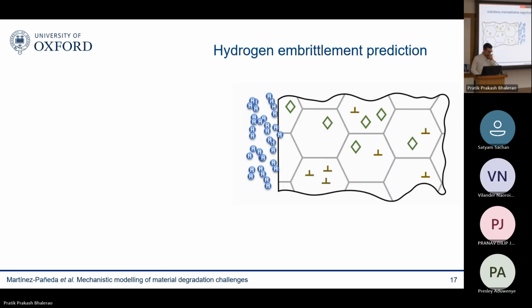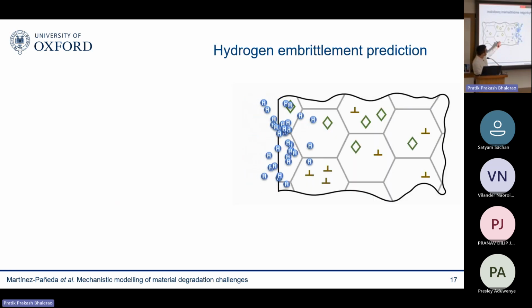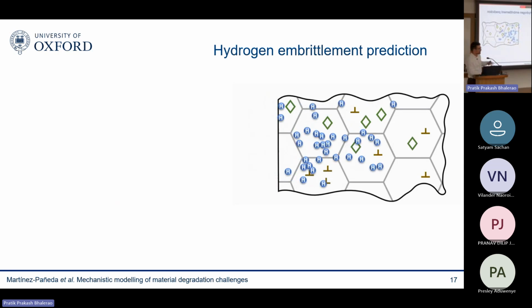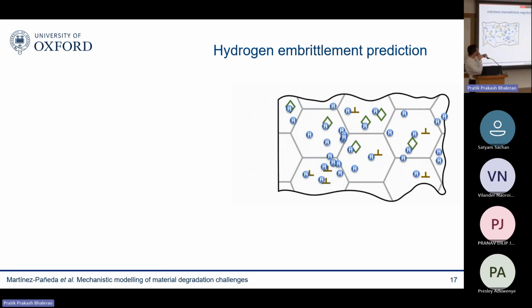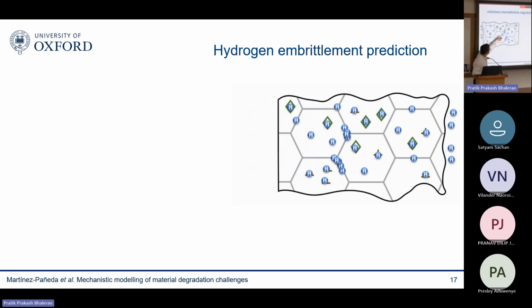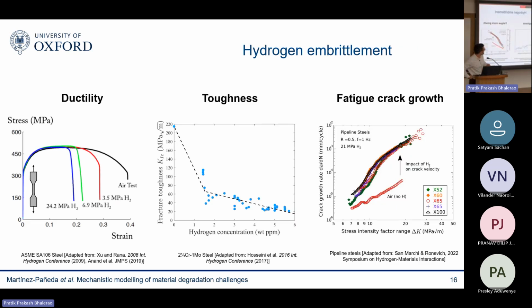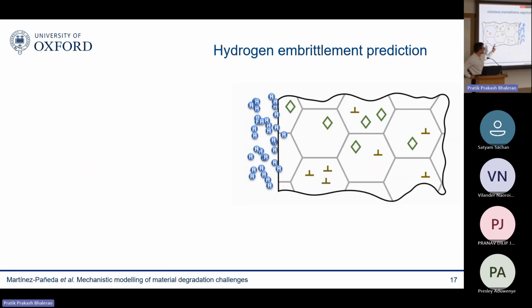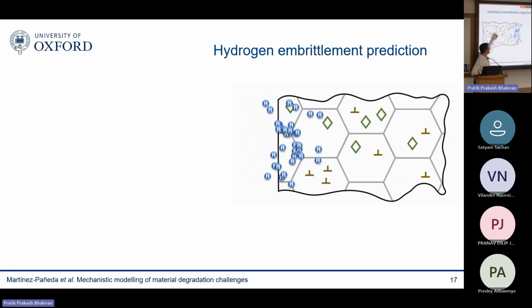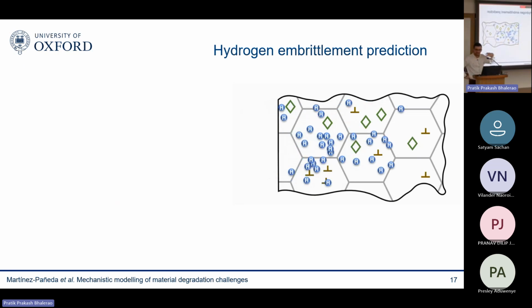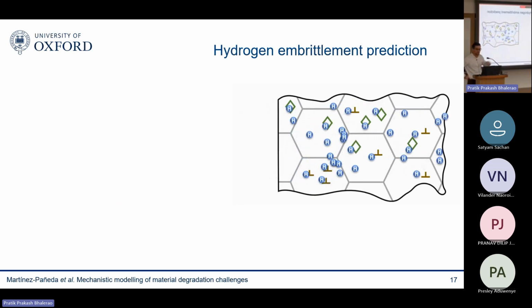And basically, this is what you want to model. So you have some hydrogen atoms coming into the material. Those hydrogen atoms travel through the crystal lattice. They are sequestered or trapped at some microstructural defects. And then eventually, when they are trapped in critical interfaces, they cause fracture. This is kind of the schematic. Let me maybe play it once again. So this is more or less the big picture. So you have hydrogen coming into your metal, coming from anywhere. It could be gas or an electrochemical environment. I'm not going to discuss that.